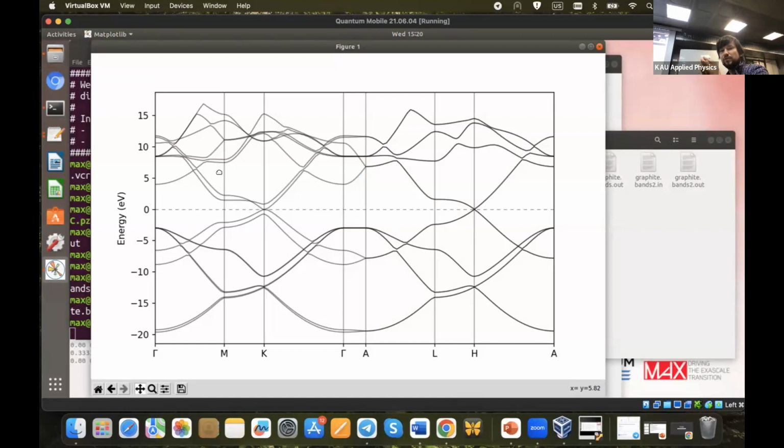That's why we saw this huge decrease in the c lattice parameter, because we chose a very simple functional, the Perdew-Zunger LDA functional. It calculates the distance between graphite layers not ideally, rather badly, I should say, with an error of like 15 or 20%.